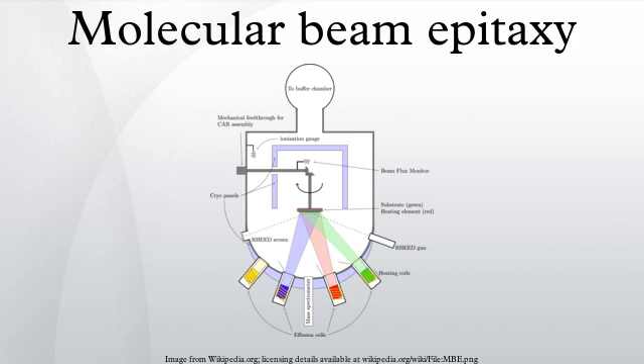The ATG instability, also known as the Grinfeld instability, is an elastic instability often encountered during molecular beam epitaxy. If there is a mismatch between the lattice sizes of the growing film and the supporting crystal, elastic energy will be accumulated in the growing film. At some critical height, the free energy of the film can be lowered if the film breaks into isolated islands, where the tension can be relaxed laterally.